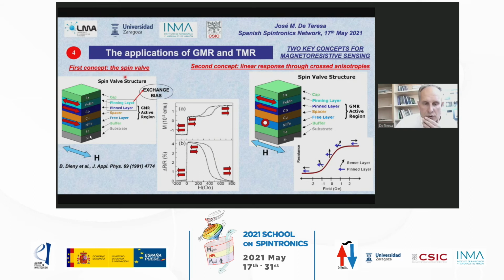The first concept, which was proposed and developed by Bernard Dieny and Stuart Parkin at IBM, was the following, which you probably are aware of, in which one of the ferromagnetic layers becomes pinned by the presence of an antiferromagnet. So due to the exchange bias interaction at the interface between the antiferromagnet and the ferromagnet, you block the magnetization direction of the hard magnetic layer. And then you have the non-magnetic spacer, and you have the free magnetic layer. So this material is chosen to have a low coercive field, so that when you measure magnetization as a function of field, you pass from a parallel magnetic configuration to an antiparallel magnetic configuration at low field, and you would have to apply a very high field in order to overcome this exchange bias field here.